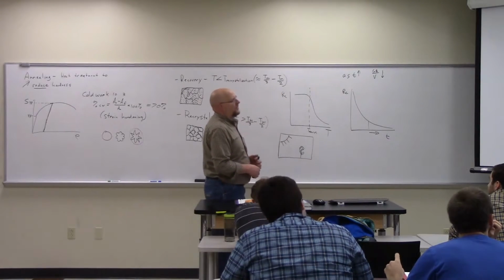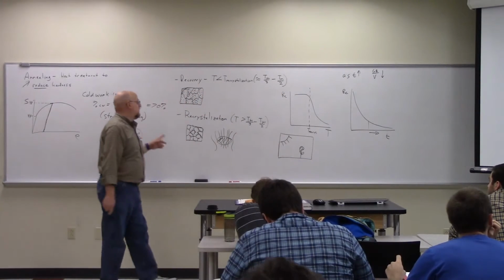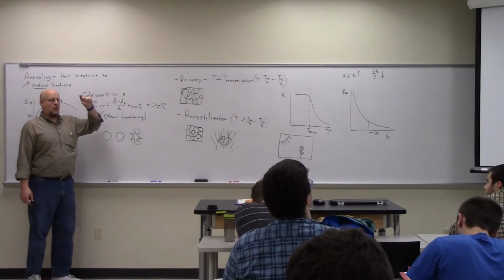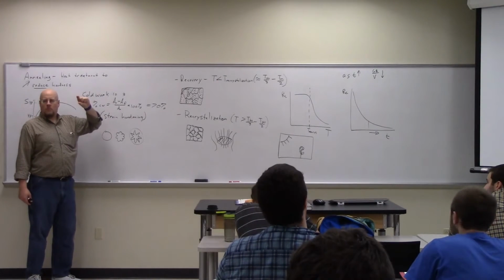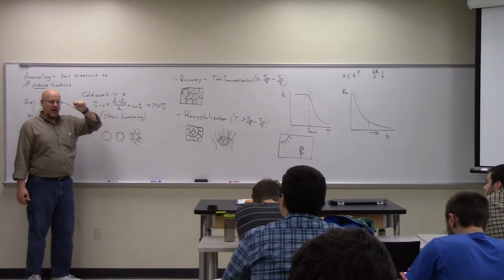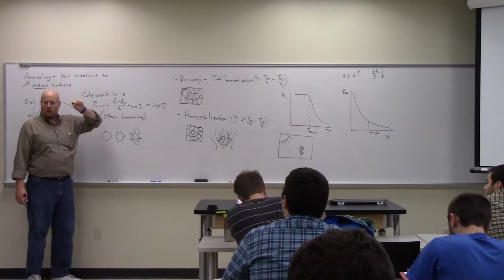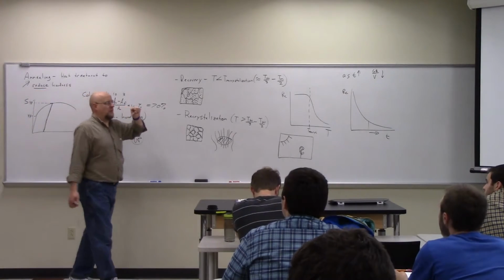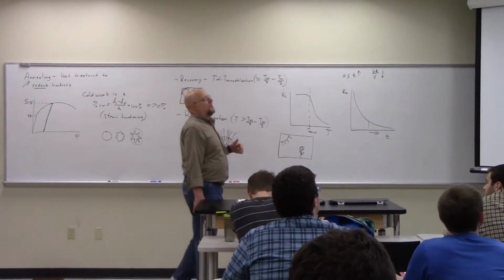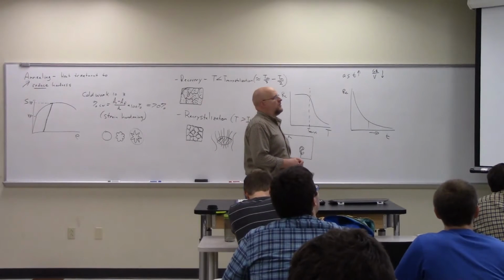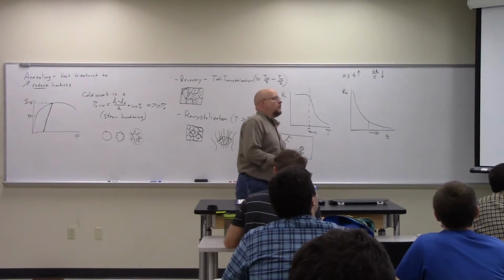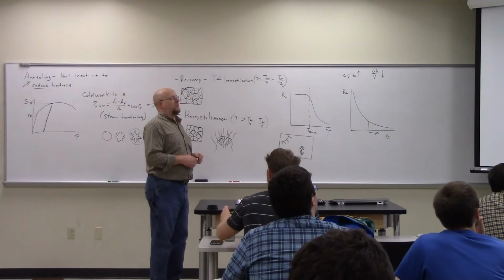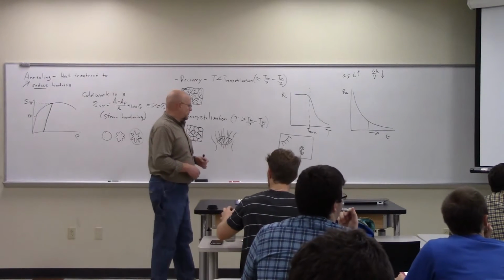For a 75% cold worked aluminum alloy, we took a 1-inch thick alloy and ran it through a die, rolling it down to 1/4 inch thick. So it's a pretty substantial amount of cold work. TR is 100 hours at 250 degrees C, and only 10 hours at 280 degrees C. We're supposed to calculate the activation energy for this recrystallization process.